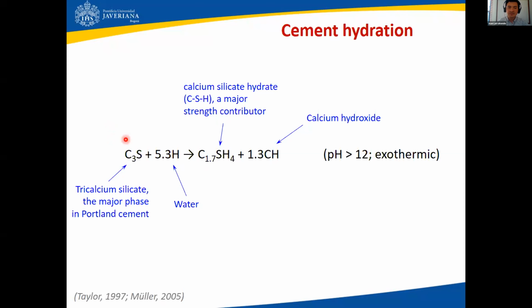So cement has a major chemical phase, which is called tricalcium silicate. And by the way, in these reactions, I'm not presenting the typical stoichiometry with the chemical elements per se, but I'm using cement chemistry notation. So I'm using the language that cement chemists use, which is just shorter terms for each one. So this C is not carbon, by the way. This C means calcium oxide. S is silicon oxide, and H is water for this notation, and that's the way cement chemists talk. So tricalcium silicate is the major phase in Portland cement, is this formula here. And when it reacts with water, it basically produces two major products.